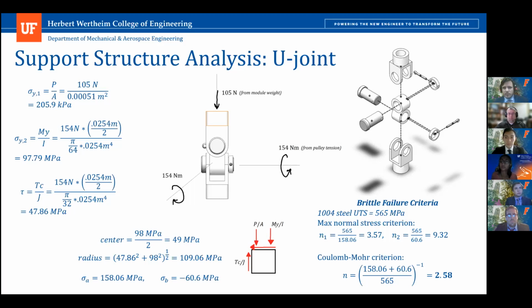And then because the biggest stresses were acting on the seal pins, we compared the principal stresses that we found to the tensile strength of that steel, and we put it into 2 different brittle failure criteria because that material is considered to be brittle, and we ended up finding a lowest factor of safety of 2.58, which does exceed the customer need of having a factor of safety of at least 2.